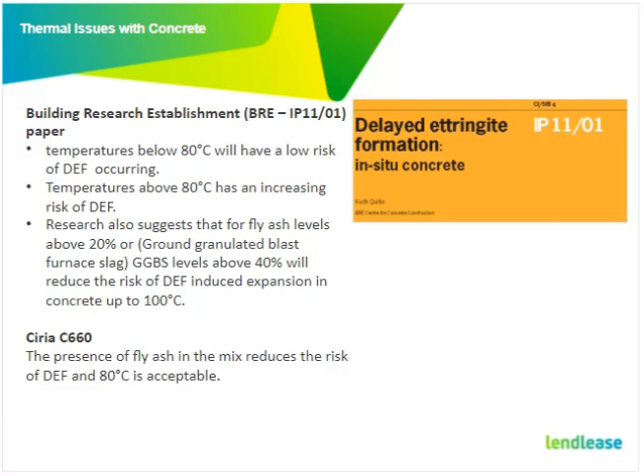A lot of our concrete mixes these days have these additives either as a minimum or we apply them. Ciria C660 is another well-known code or guideline. It also suggests that if you've got the presence of fly ash in the mix, it reduces the risk of delayed ettringite formation, and 80 degrees is acceptable for specifications.